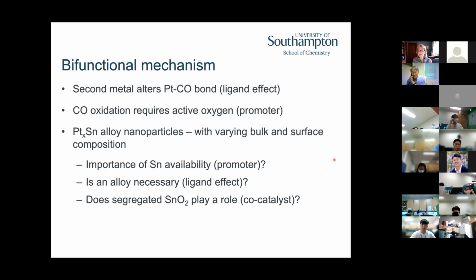Well, the second metal is thought to act by this bifunctional mechanism. The second metal alters the strength of the platinum-CO bond. That's the ligand effect in thermal catalysis. It activates the oxygen at a lower potential. That's a promotion effect in thermal catalysis. By varying the bulk and surface composition, we should be able to separate these two.